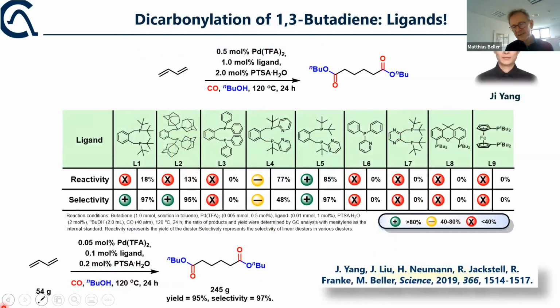So testing this type of ligands, this is the Lucite ligand. You see the reactivity is too low for an industrial product. It has nice selectivity, but the reactivity is too low. Steric modification doesn't change much. Electronically, the aliphatic phosphines are very important. Our ligand, again, is much more active than the Lucite ligand, but the selectivity was not good in this case. So we had a significant amount of branched diacid. And that's, of course, not useful for making adipic acid.